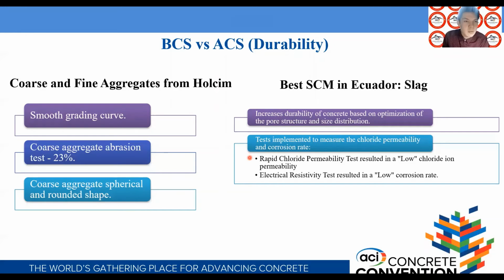Tests were implemented to measure the chloride permeability and corrosion rate, such as the rapid chloride permeability test, which resulted in a reduction of the total charge passing through the concrete. That means a better resistance against chloride ions. And the electrical resistivity tests show an increase in electrical resistivity. That means a lower corrosion rate.